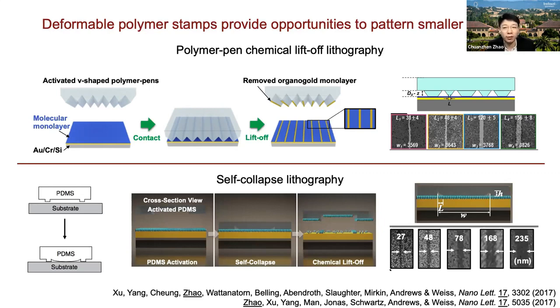Well, it turns out it's not, for me. Here we developed a new lithography technique called self-collapse lithography, which utilizes those nanoscale channels formed naturally at the edges of microscale features on softer stamps. By tuning the height, the width, and also the Young's modulus of the stamp, we were able to fabricate nanoscale features down to 30 nanometers. The most exciting aspect of this lithography is that small features are produced from large structures, since the patterning can be achieved using those microscale stamps made by conventional photolithography, which avoids the use of expensive tools such as e-beam lithography.